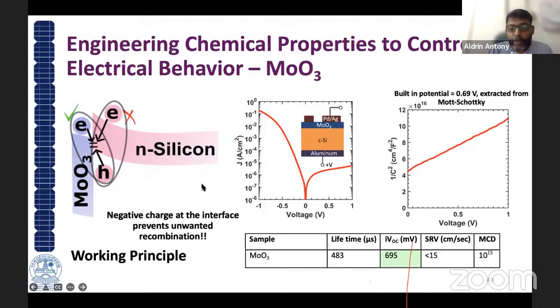And we tried to fabricate a junction like a dark diode like this, using crystalline silicon. We put MoO3 over the N-type crystalline silicon and put metal contacts of palladium and silver. If you apply a bias to this diode, you can see it works exactly like a diode. It has diode characteristics: a low reverse saturation current, and the diode current increases exponentially.